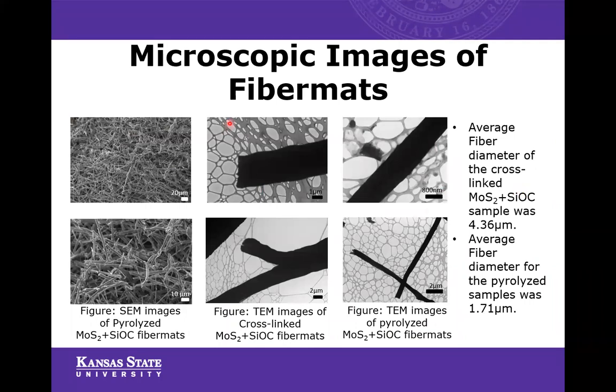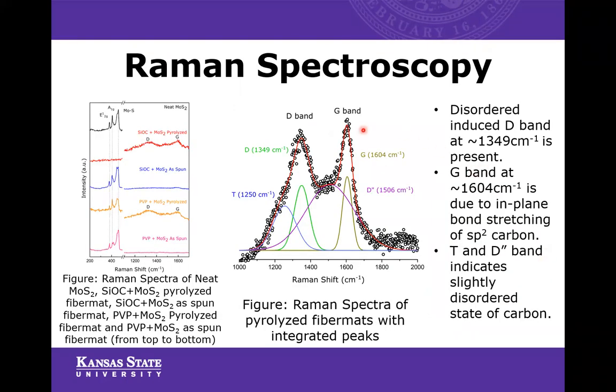So for the analysis part, here are the microscopic images of the fibermats. The scanning electron microscopic images of the pyrolyzed MoS2 SiOC fibermats showed that the fibers were uniform, no beads or anomalies were observed. The TEM or transmission electron microscopic images of the cross-linked and the pyrolyzed fibermats were also observed. From there, we see that the fibers are solid. The diameter of the cross-linked fiber was on average 4.36 micrometer, and for the pyrolyzed sample, the fiber diameter was 1.71 micrometer.